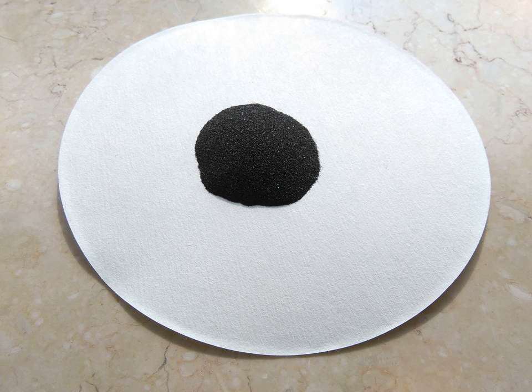Because of the volatility of SiO, silica can be removed from ores or minerals by heating them with silicon to produce gaseous SiO in this manner. However, due to the difficulties associated with accurately measuring its vapor pressure, and because of the dependency on the specifics of the experimental design, various values have been reported in the literature for the vapor pressure of SiO(g). For the pressure above molten silicon in a quartz silicon oxide crucible at the melting point of silicon, one study yielded a value of 0.002 atmospheres. For the direct vaporization of pure, amorphous SiO solid, 0.001 atmospheres has been reported. For a coating system, at the phase boundary between silicon oxide and a silicide, 0.01 atmospheres was reported.